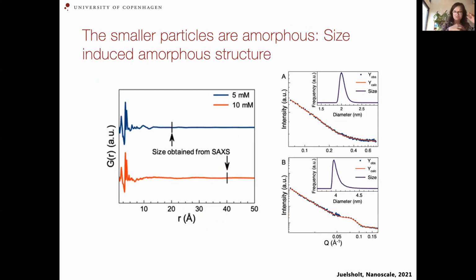So these were the large structures, so we could establish the structure of the nanorods, but we also had these much smaller particles, which we were synthesizing with lower concentrations. And here what we did was to collect PDF data from them, and we had these PDFs here, 5 millimolar and 10 millimolar, and you see we only have local structure, clear PDF peaks at very low r values. And that means that in the structure, we only have ordering of the atoms very locally. And this is consistent with an amorphous structure.